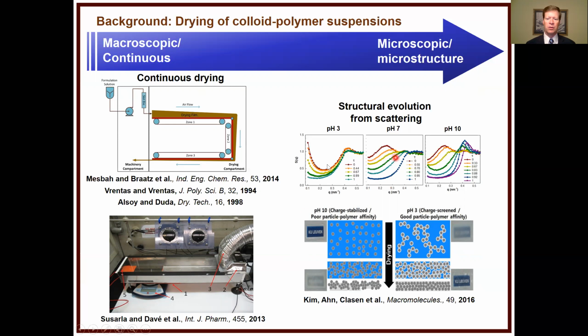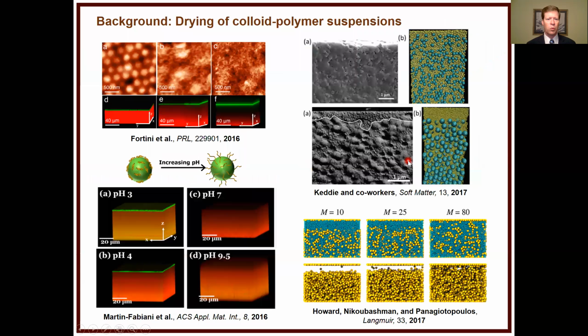And so, for instance, you could look at the particle assembly in these systems by looking at scattering. So if you send something to scatter through these films, I believe this is X-ray scattering, you can see maybe at different times in the film whether the particles were well distributed or they're aggregated and how that changes. And here, pH was used to change the relative attractions between particles. And so our study today is actually closest to this. This might be not quite as familiar to the coating world, but certainly there's a lot of people in this field that have combined colloids and coatings and then looked very closely at how the microstructure evolves.